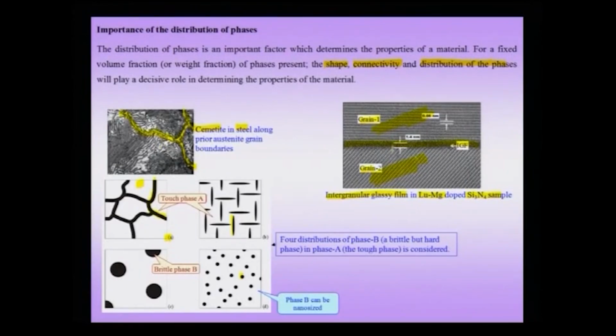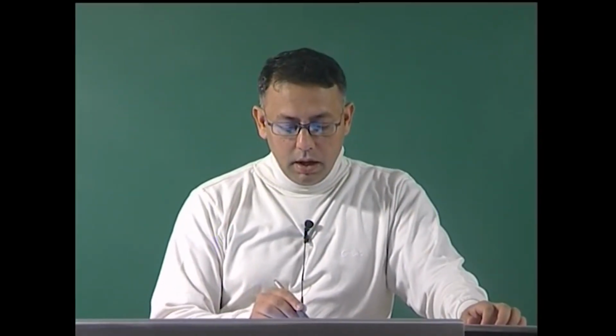Now, we had considered 4 schematic examples, and in some sense it was this example A which was exemplified in the example of steel and the case of the silicon nitride sample. In one case, there was a crystalline phase like cementite along the prior austenite grain boundaries, and in the second case it was actually an amorphous film. And if you look carefully at the scale bar, this film happens to be in the nanoscale. While the silicon nitride grains are large grains and not nanoscale, only this intergranular glassy film is in the nanoscale, and that too in the dimension marked in the figure. Therefore, I need to worry about the connectivity of the phase B, its distribution, etc.